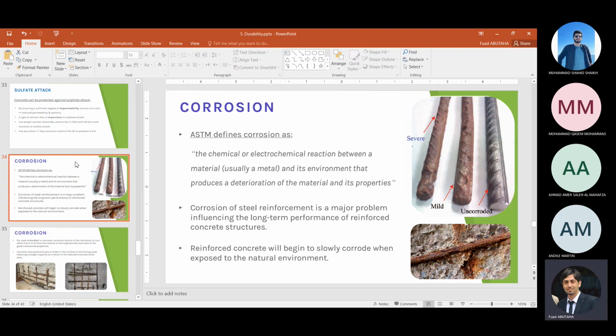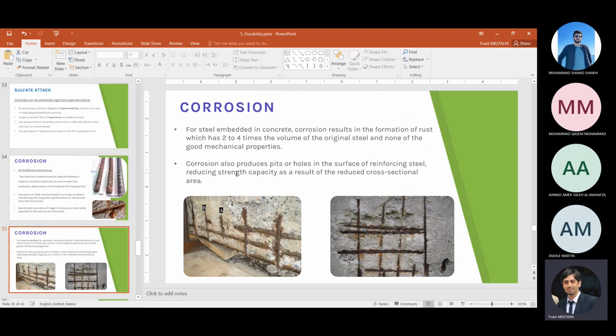So when reinforced concrete gets in contact with water, corrosion will start, and we start to see the volume of the steel increase as a result of this chemical reaction that will end up with structure failure. Reinforced concrete will begin to slowly corrode when exposed to a natural environment. For steel embedded in the concrete, corrosion results in the formation of rust, which has 2 to 4 times the volume of the original steel.